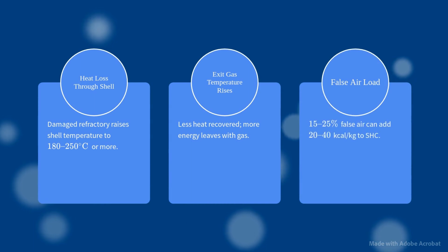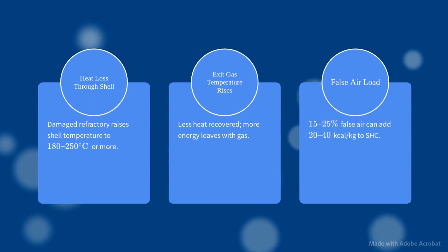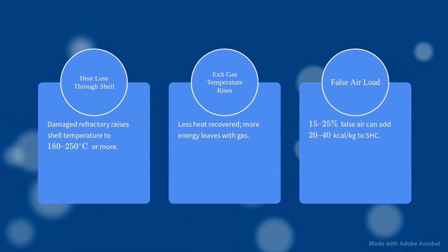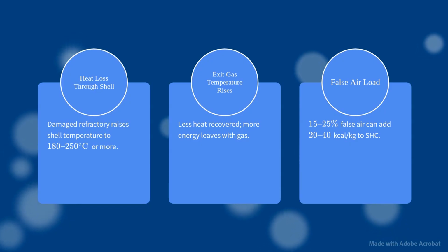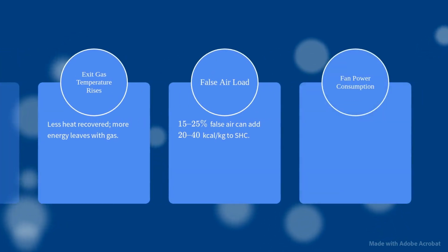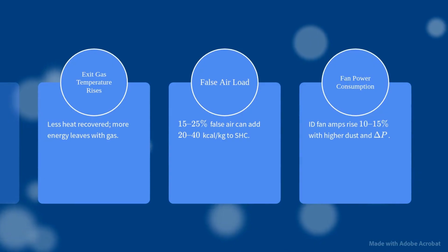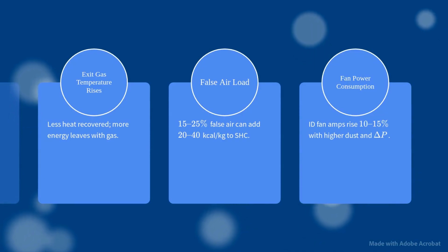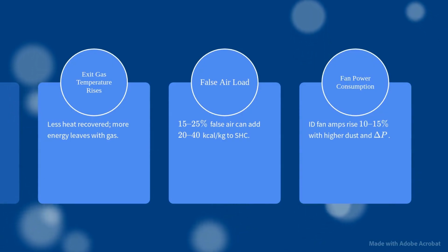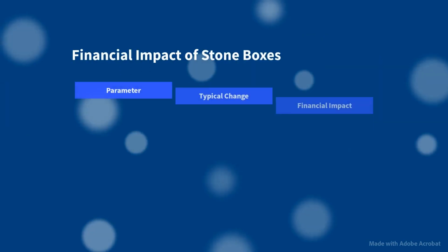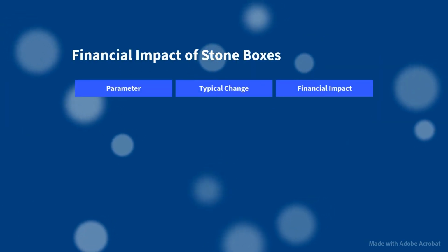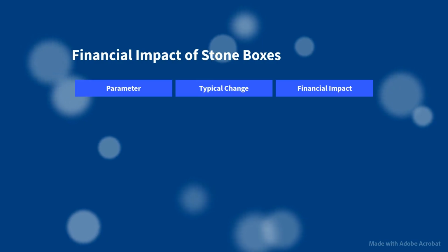False air load is a major factor. When false air infiltration reaches between 15 and 25%, it can add 20 to 40 kilocalories per kilogram to SHC. Fan power consumption increases as the ID fan amps rise by 10 to 15% due to higher dust loading and pressure drop. Notice how these factors combine to create a significant financial burden over time, even when production appears stable.